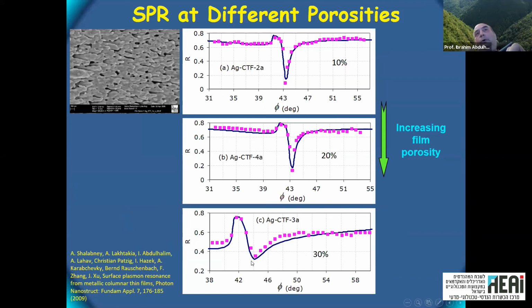But if you increase more, this resonance becomes very wide. So it becomes useless, actually. You can think about it. When the porosity is large, the metal is not conducting anymore. So it's not a good metal, actually, and you will not get a good extended plasmon. But maybe you start to get a localized one.